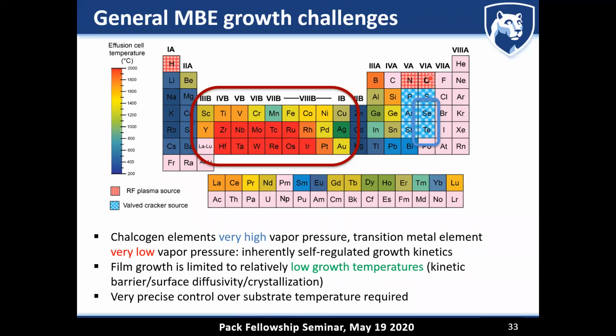But now let's say we want to switch the element in group 16. We want to go to chalcogenides, and these are layered compounds. They show topological insulating properties, and they typically come in layered structures. So they're basically researched a lot right now. And so the question is, if you want to grow them by molecular beam epitaxy, what's the problem? And the problem is that these chalcogen elements have very high vapor pressure, while the transition metal elements that you probably want to marry them with have very, very low vapor pressure. And so that makes it very complicated to combine those as a film.